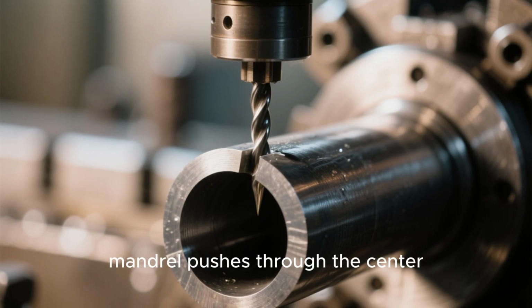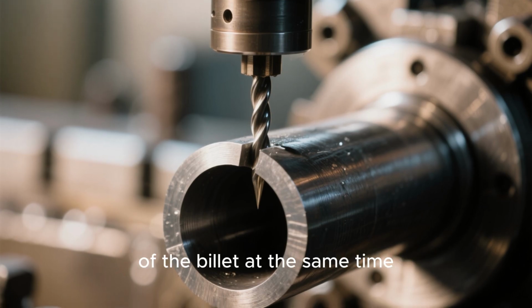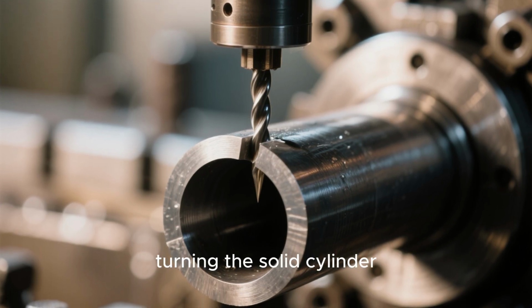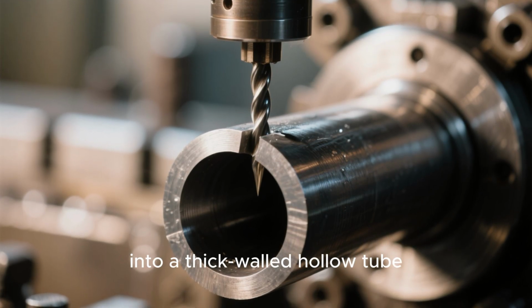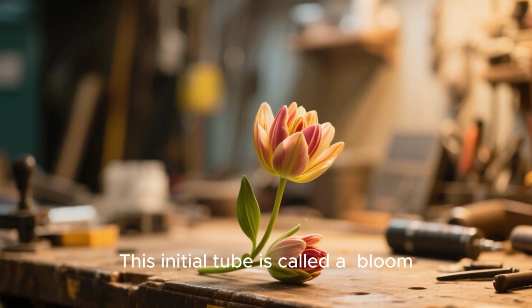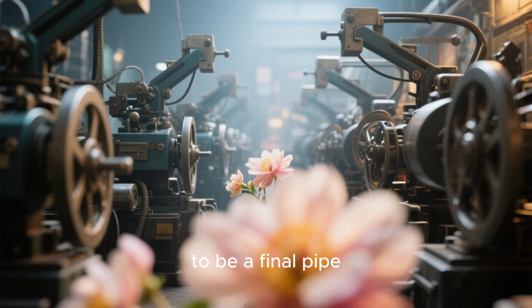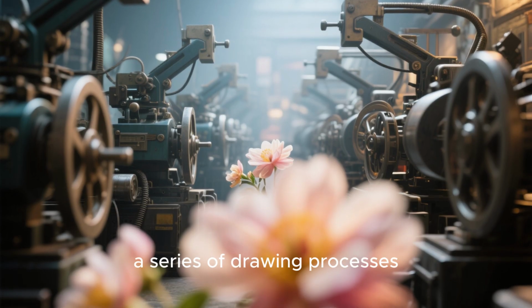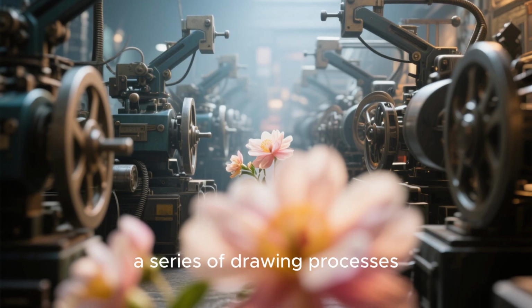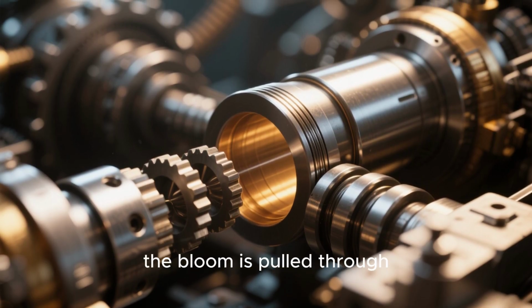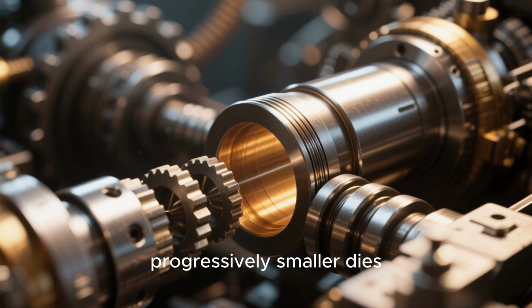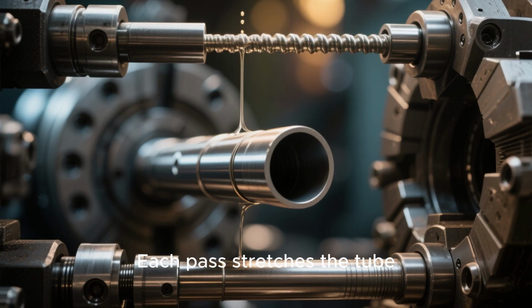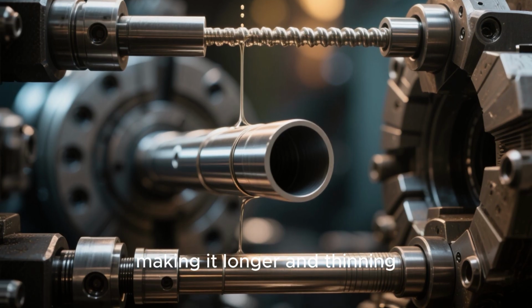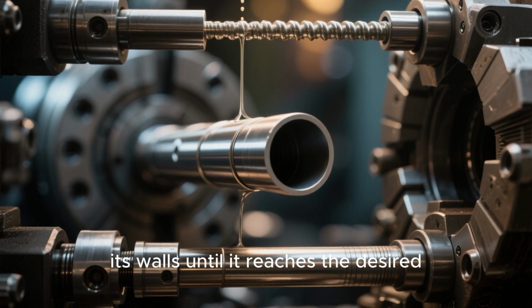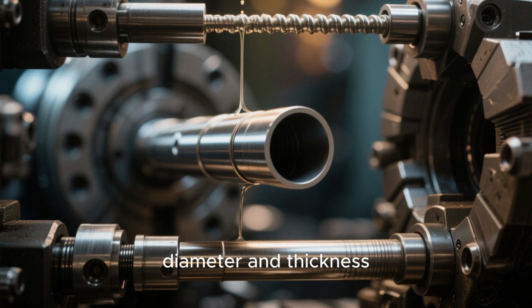However, a piercing mandrel pushes through the center of the billet at the same time, turning the solid cylinder into a thick-walled hollow tube. This initial tube is called a bloom. The bloom is still too thick to be a final pipe, so it goes through a series of drawing processes. In a process called tube drawing, the bloom is pulled through progressively smaller dies. Each pass stretches the tube, making it longer and thinning its walls until it reaches the desired diameter and thickness.